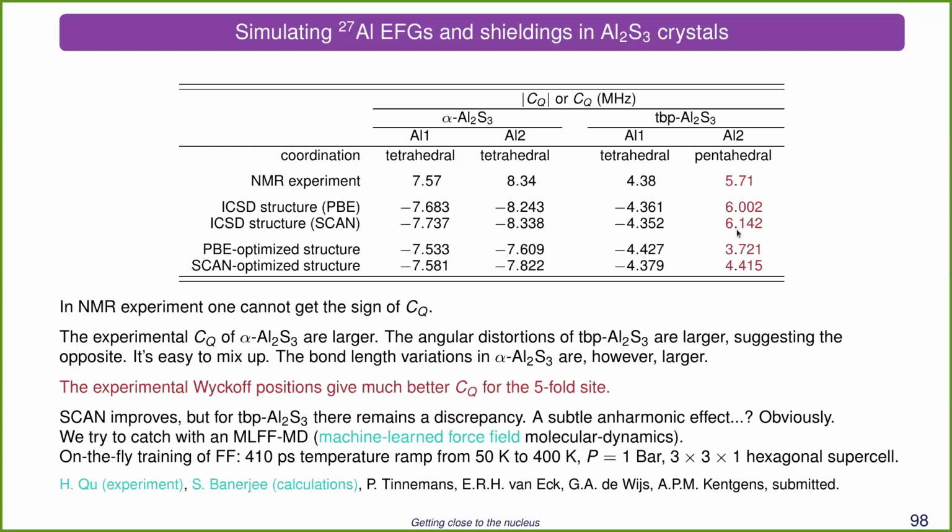And how can we catch this? Well, we can catch this by sampling the temperature dependence, by doing a molecular dynamics simulation of the crystal, measuring the tensor and averaging the tensor. That's what we should do. That's not actually what we do. We calculate the time averaged positions as a function of temperature with the molecular dynamics. You can use machine learned force fields for that. How to do that is not at the moment relevant. That's a completely different story, completely different workshop.